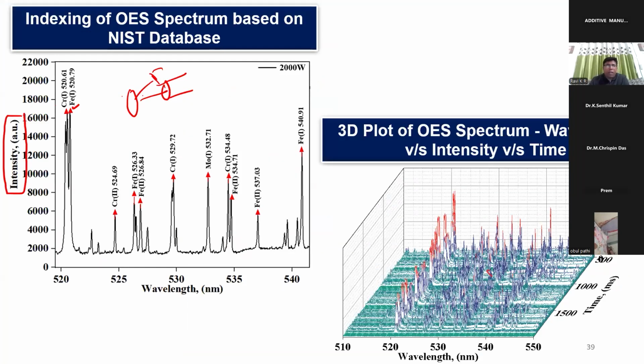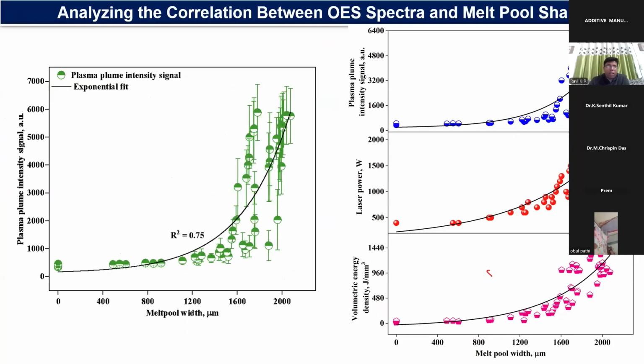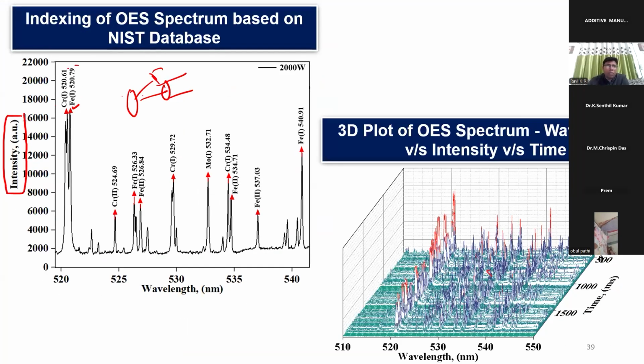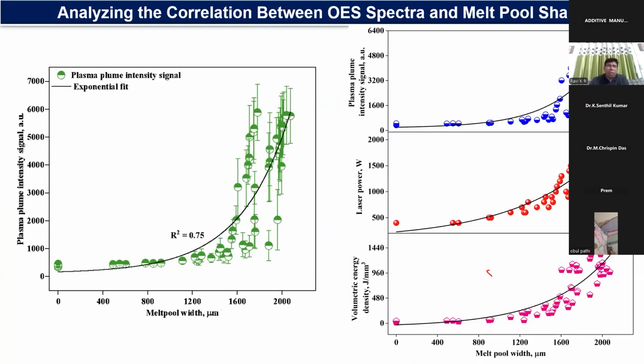Based on all the analysis, we have identified one particular wavelength which is very useful for this analysis. We took this spectrum and tried to correlate it with the melt pool width. I'll not get into too much detail. So melt pool width and intensity clearly established two parts: one is the conduction regime, another is the keyhole regime. As long as you are in the conduction regime, you will get good melt pool geometry, giving you parts without any defects.